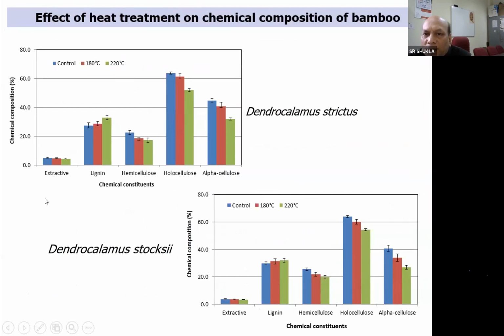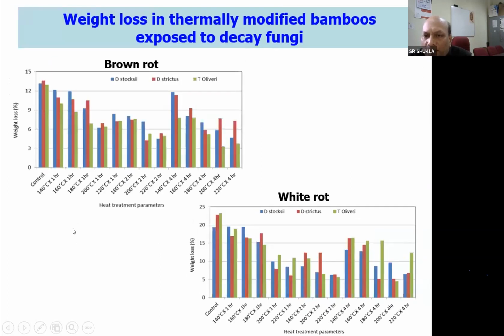As I told, this thermal modification will change the chemicals which are present in the bamboo. So this shows the amount of changes in the chemicals, like extractives, and the amount of lignin will be improved. At the same time, there is a degradation in the hemicellulose. The hemicellulose percentage will go down, and this is holocellulose and this is alpha cellulose in different bamboo. Because the amount of hemicellulose degrades, that's why the bamboo becomes more dimensionally stable and less hygroscopic.